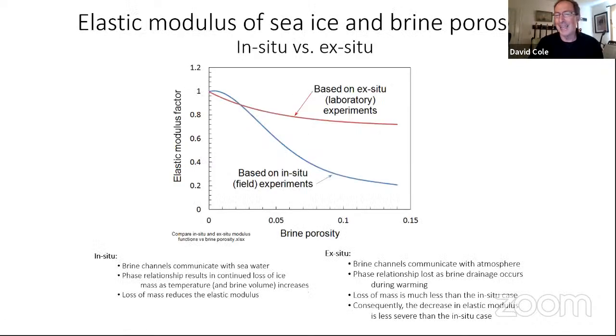So, all right, I want to get this out there. We're still thinking about this and trying to understand the underlying mechanisms. But let me just state this as an empirical observation: when we do experiments on either laboratory-prepared saline cores or sea ice cores that have been transported back to the lab and tested, we get this red curve for the behavior of the modulus as a function of brine porosity. Now, what I'm plotting here is just a modulus factor. So this would be whatever temperature-dependent and crystallography-dependent modulus you have for the pure ice case.